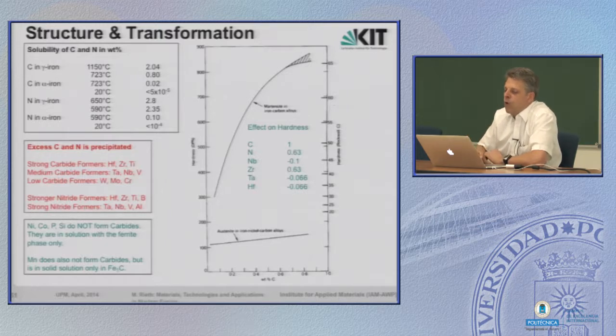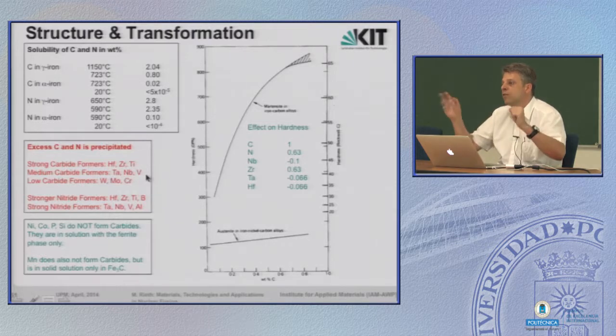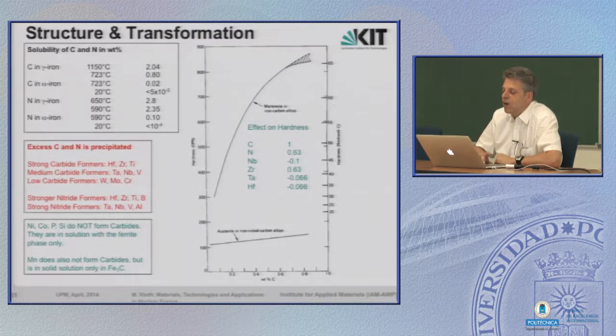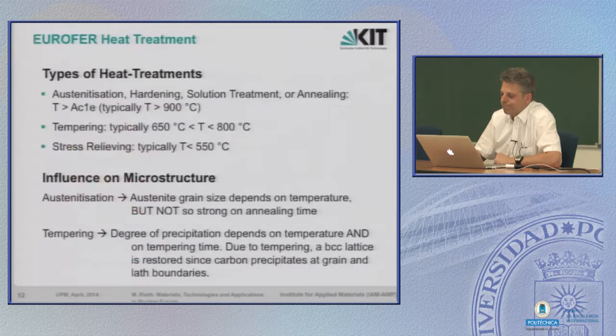That's carbide formers. And strong carbide formers are hafnium, zirconium, titanium. We don't have this in the Eurofer steel, but we have tantalum. And we have vanadium. So first, carbon forms vanadium carbides, tantalum carbides. And the remaining amount meets the 1% tungsten in Eurofer and forms tungsten carbides. All this happens preferably along grain boundaries, or lath boundaries, and that's where the carbon ends.